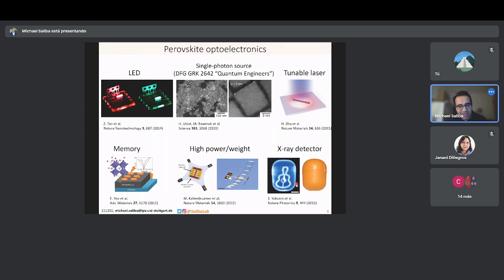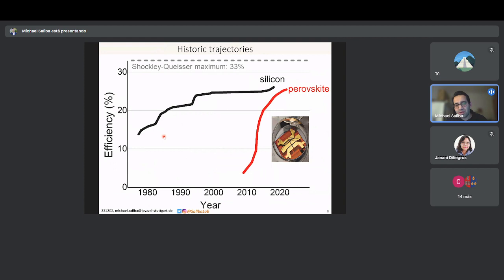Then what is, of course, relevant here, you can see it. It took many decades for silicon to reach its peak value, which is now at 26.8%. For perovskites, they started at 3.8% in 2009, and they've now reached over 25.7%, which is a remarkable journey in an extremely short time. In fact, no other material was able to cover such efficiency gains in such a short time. So it's the fastest learner in history, one may say.